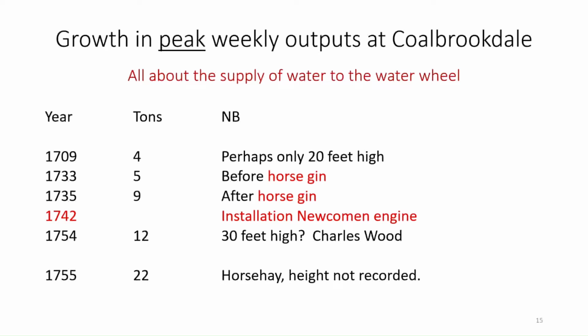Now, what did they do then to be able to get the iron into the forges by 1750? Well, what they did was build their furnaces bigger, higher in particular. But they couldn't do that in most cases without consuming an awful lot more water, because a bigger furnace required more air and therefore required more water to drive the bellows, because they were all driven by water wheels at that time. So the thermal efficiency of a blast furnace is basically set by the height of the blast furnace. The output of a blast furnace is set by the volume inside the blast furnace. So we can be reasonably sure that if they improved the output of their blast furnaces, then they were also making the furnaces bigger. And the only way they could easily make them bigger was to make them taller.